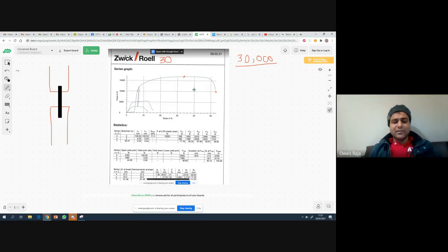Okay, these are the industrial graphs, the ones we actually use in a real industry. If you look at that one, this is the length, which is 100. The gauge length is 100. Elastic modulus is calculated here, 11.3. That's the elastic modulus. This value is 0.2% plastic strain. So 0.2% plastic strain is somewhere here, and the force value is not right. It just gives the force somewhere here, because of slippage the value is incorrect.